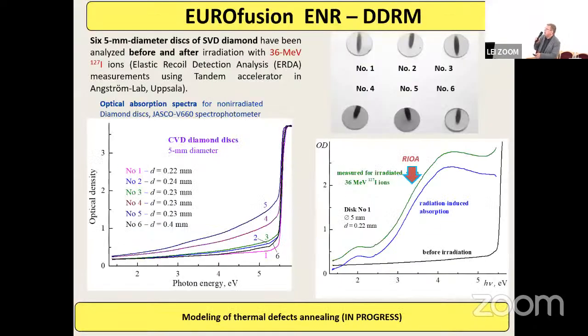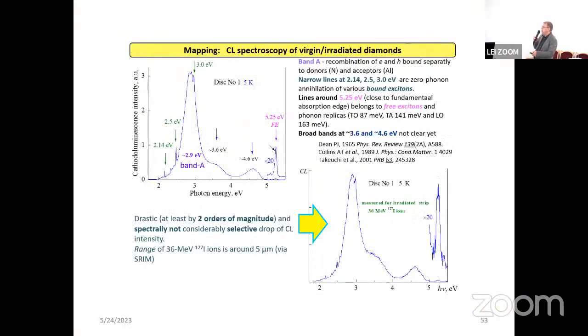And maybe the last data. This is data for diamond. We obtained a few disks from a German company working for Eurofusion that produces such diamond disks. You can see here the effect of radiation. This was just after radiation. We observed radiation damage in the region of about 4 electron volts. We also found strong degradation of the signal. What is also important, because these are quite big, is that we performed two-dimensional mapping using cathodoluminescence, Raman, and infrared. So we need to understand all properties of the disk.